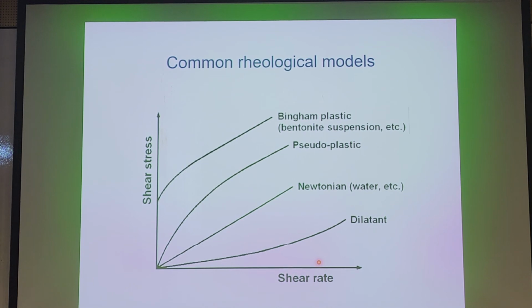There's some yield stress to get it to move, and if you don't have enough stress, it'll just come to rest and set. There are of course other types of shear thickening and shear thinning. This dilatant one, we call it shear thickening. Pseudoplastic is shear thinning, meaning that it'll get more and more water-like as you shear it at higher rates. So these are common rheological models used to describe grout. And we can, in the lab, measure the rheology of our grout before we go to the field. So this should be done as a check to make sure that the rheology that you design can be injected into the ground.